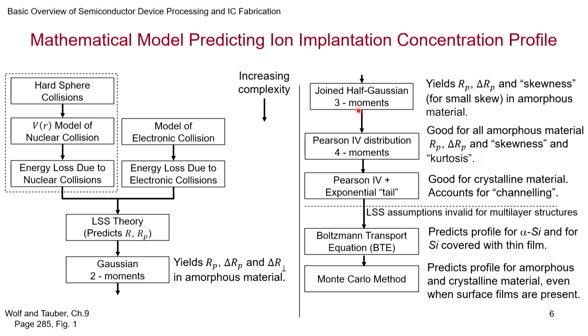The third moment ends up being the skew. So, it need not be symmetric. Gaussian is a symmetric distribution. It need not be symmetric, and practically we do see that it is not symmetric. Whatever is lighter atoms will get reflected back more. So, as a result, you will find that the concentration is towards the direction from which it comes. Heavier atoms, on the other hand, may be having a center of gravity or center of first moment on the other side. So, it need not be symmetric.